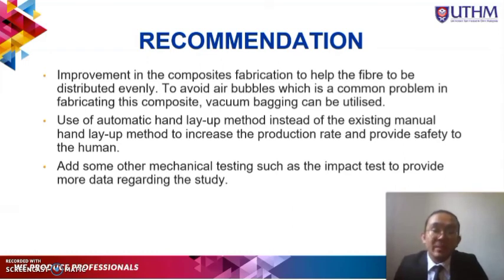Alright, for the recommendation, improvement in the composite fabrication to help the fiber be distributed evenly and avoid air bubbles, which is a common problem in fabricating this composite. Vacuum bagging can be utilized.